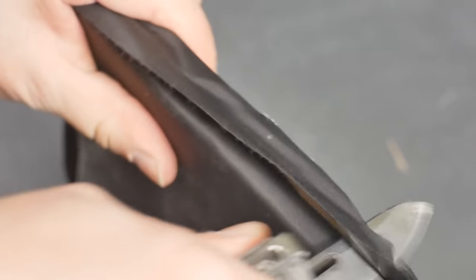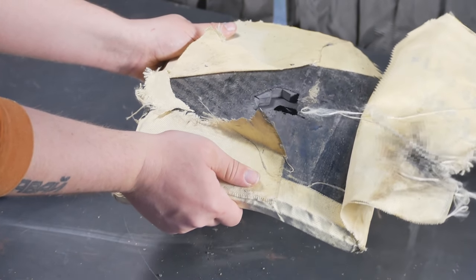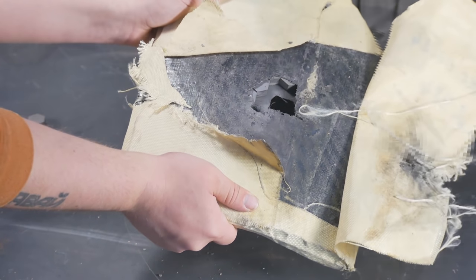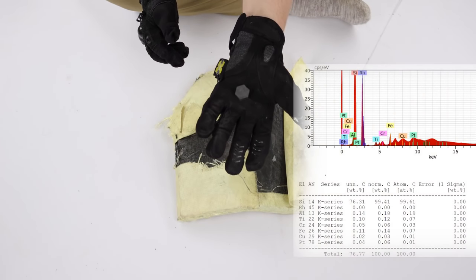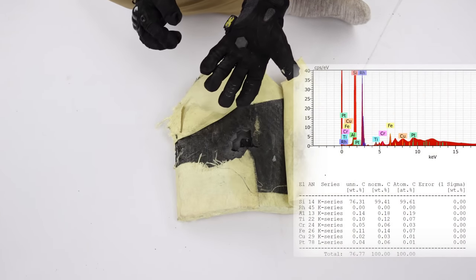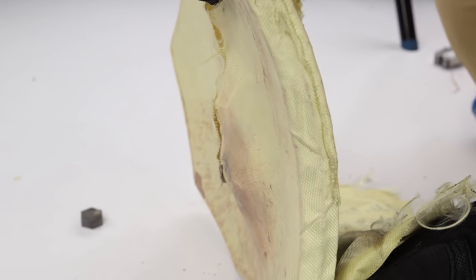Let's do an autopsy. Removing the waterproof cover reveals a thin layer of aramid surrounding a carbon fiber wrapped plate composed of hexagonal ceramic tiles and a polyethylene backer. Under a spectrometer, these tiles are revealed to consist of silicon carbide. This combination of ballistic materials is pretty reminiscent of a few higher-end Western NIJ Level 4 plates, and if you recognize any specific similarity, please leave a comment.